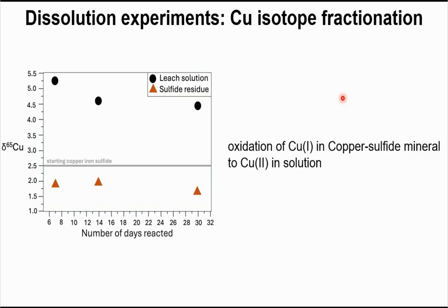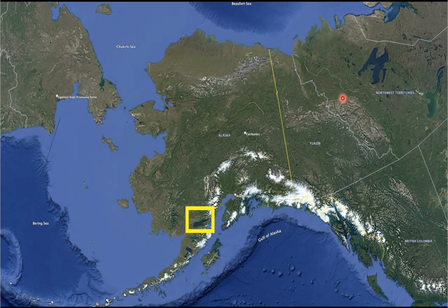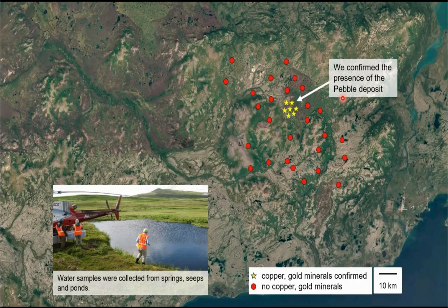And that oxidation, where oxidized copper species favor heavy bonds, that oxidation of copper 1+ to 2+ results in the signal that we see in the water. So we then said, let's test it. So we went to this remote area in Alaska and we collected water samples from springs and seeps and ponds like the one shown on the bottom left.